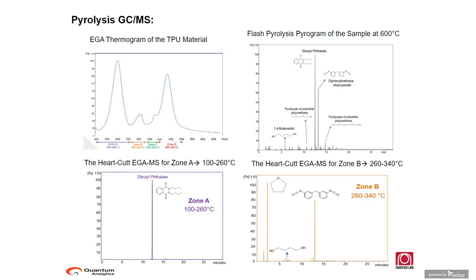We have analyzed, and I'll show you why we did this a priori, because this TPU was commercially available, and we were curious, if not cautious, about what ingredients were used before 3D printing them and mixing them with graphene. So from the EGA thermogram, we confirmed that the typical composition can be divided into 4 zones, zone A, B, C, and D. And each zone can be focused on a particular composition. And from the flash pyrolysis up to 600 degrees C, what we confirm is that we have a distribution of phthalates, isocyanates, and polyols for the whole composition.